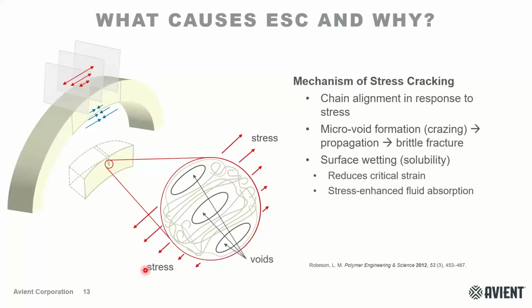And as these microvoids start to develop, you can start to see crazing on the part in a plane that's normal or perpendicular to the stresses. And so that's what we see as crazing. And as those cracks or as those microvoids continue to grow, eventually the stresses can become too much for the chains, and you'll see chain pullout or potentially chain scission, which will ultimately lead to cracking and then moving the stress down into the deeper layers of the part. And so you can see how this thing would sort of propagate and lead to brittle fracture.